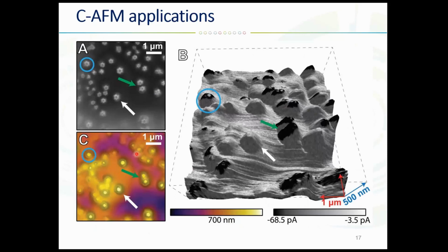Here semiconductor nanowires were used. These nanowires are quite a promising material for photovoltaic applications because they have superior light absorption, and they're very thin as well. Here the conductive AFM was used to map the surface topography and the current distribution of this sample. We were applying a constant voltage between the scanning conductive tip and the sample surface. The main advantage of conductive AFM is the possibility to access local conductivity information down to the nanoscale. So this is one of the possible applications of conductive AFM. It can be quite useful.